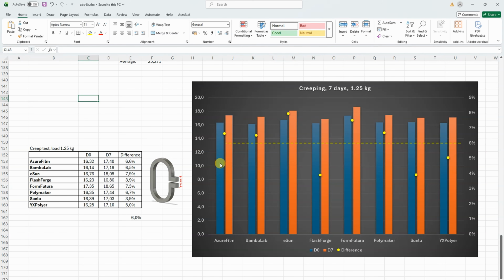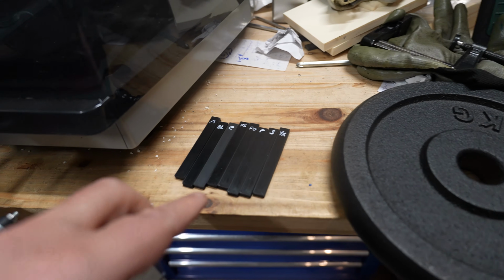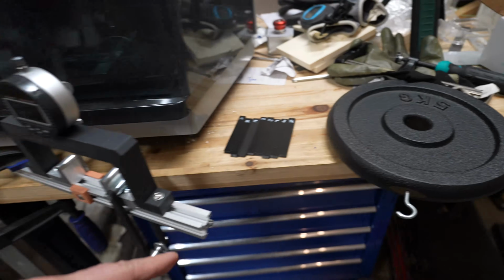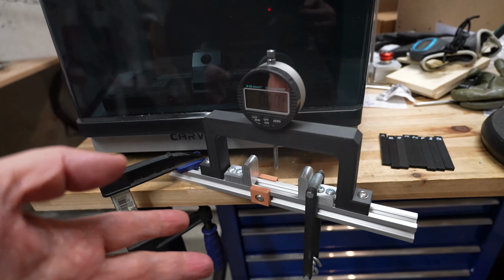And with the blue, this is initial deformation, distance between 2 reference surfaces, and with the orange, this is a deformation after 7 days. And the difference between two in percentage is marked with this yellow point, and 6% is the average. So in this case, worst creeping was by the eSun and FormFutura, and two best are FlashForge and Sunlu. And now 3-point bending test, where we place this load and measure the deformation after exactly 30 seconds.